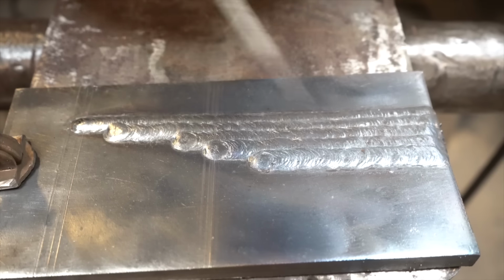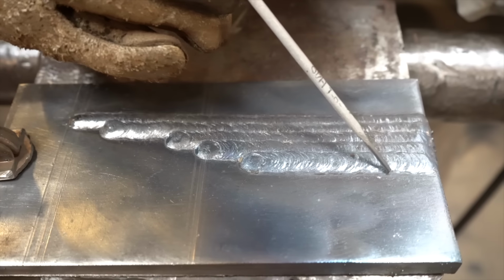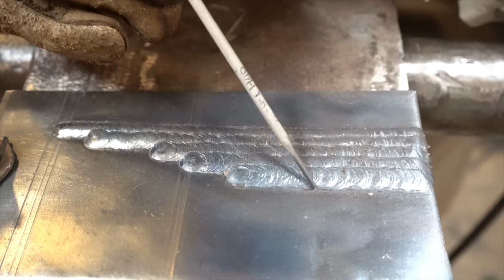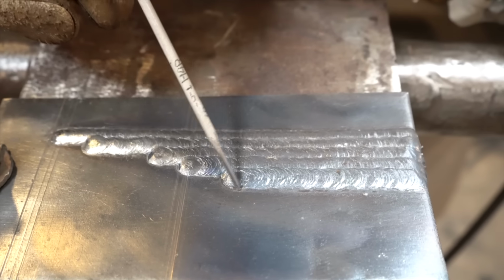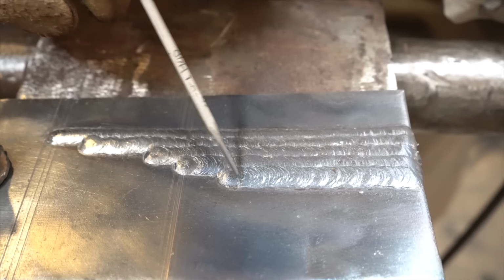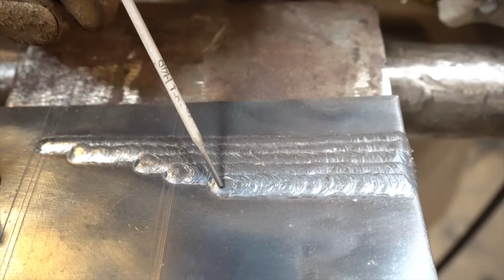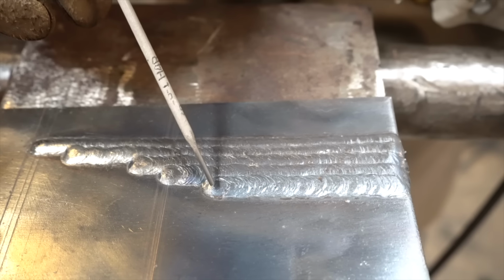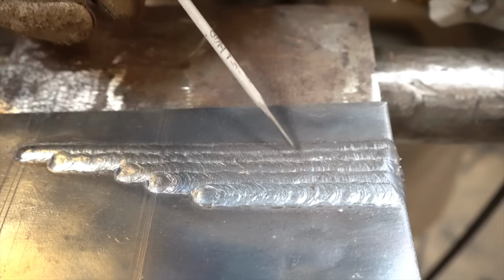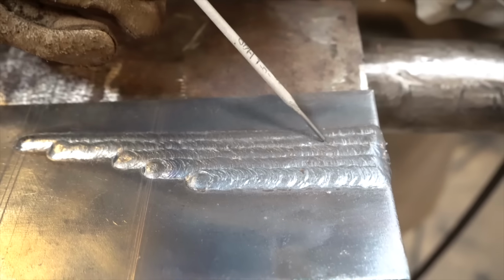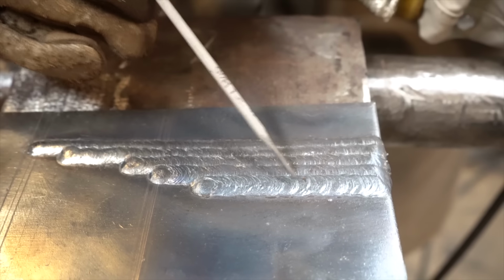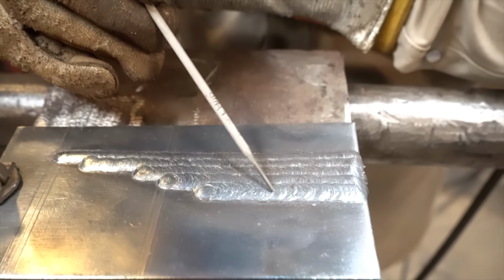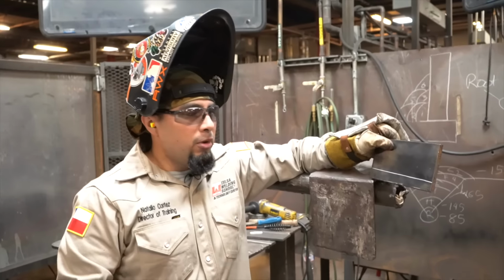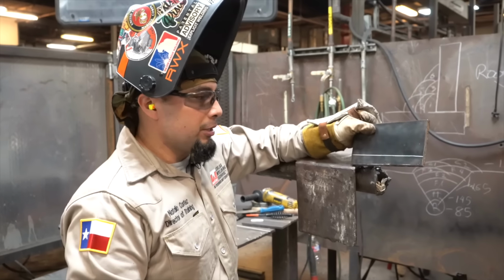After that, just staying on the top edge of the previous weld, keeping that puddle consistently the same width, the same length, and watching your arc length. If you watch all those steps, you'll get this perfect overlap, which is about 50% on each weld, covering 50% of the previous weld. Now we're moving on to our horizontal welds.